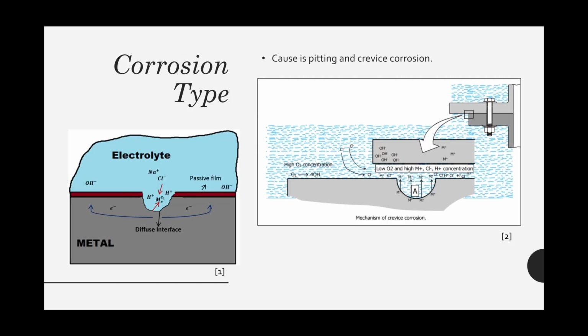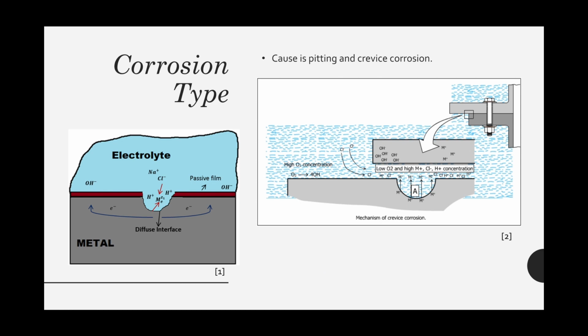The two most likely causes of corrosion in this item are pitting and crevice corrosion. The reason for this is because the corrosion pattern on open areas of the surface visually resembles the dispersion of pitting corrosion. Likely causes of this are scratches and nicks in the metal surface. Concentration cells such as the diagram on the left-hand side can then form.